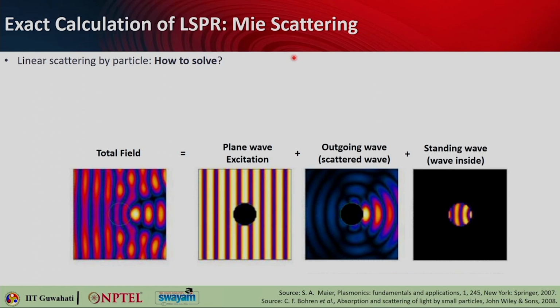In an experiment, people made colloids of gold and silver nanoparticles of different sizes, and all of them looked different in color. So, there has to be some relationship between the size of the particles and the wavelength and color they strongly scatter or reflect. That theory is known as Mie theory.